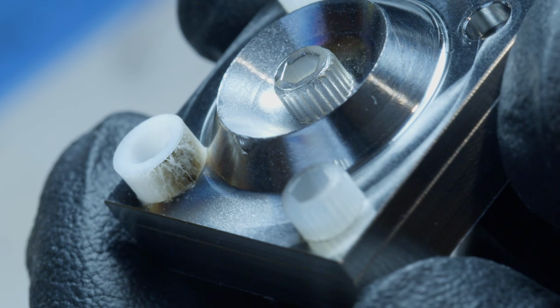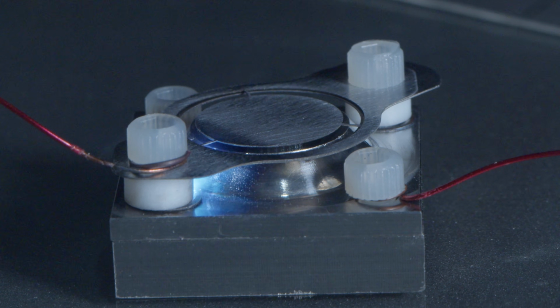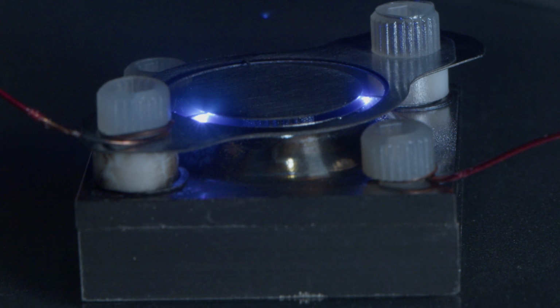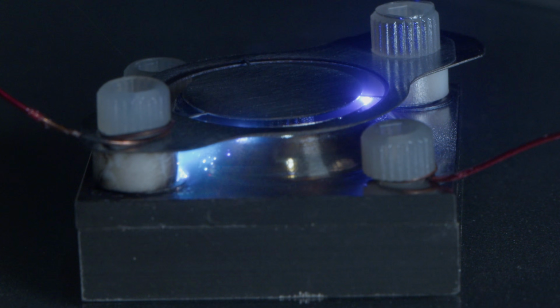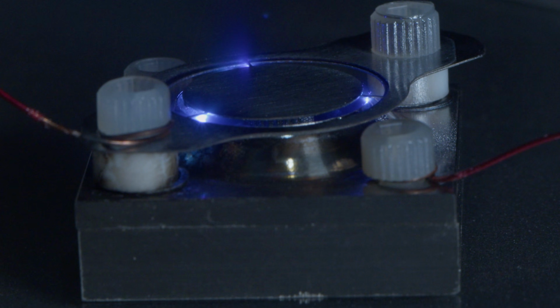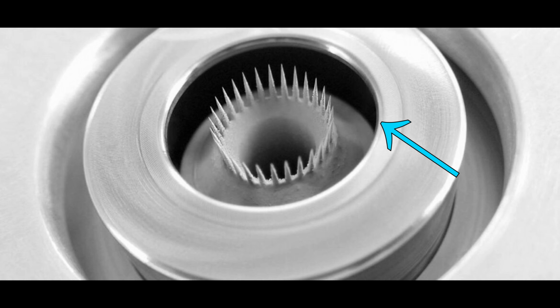I tried reducing the size of the bridge. Here it's only 0.5 millimeters wide, but it still was too big and we had the same problems. So eventually I removed the inner electrode entirely. The ion thrusters actually only have an outer ring, so in theory it should work.